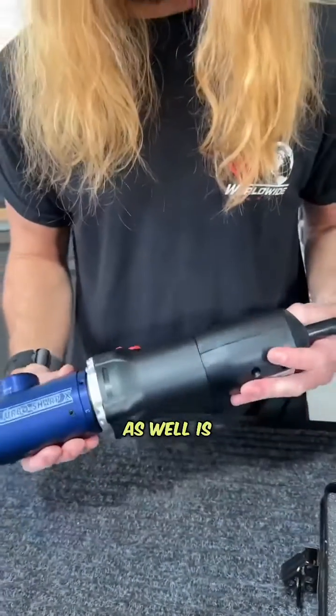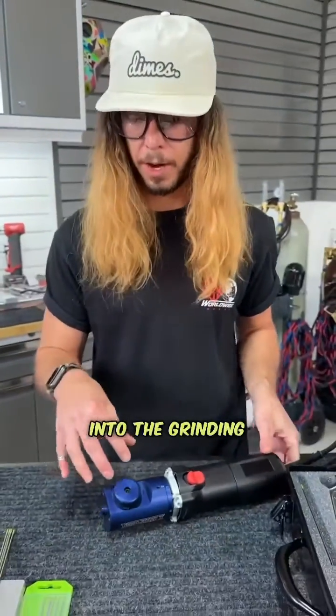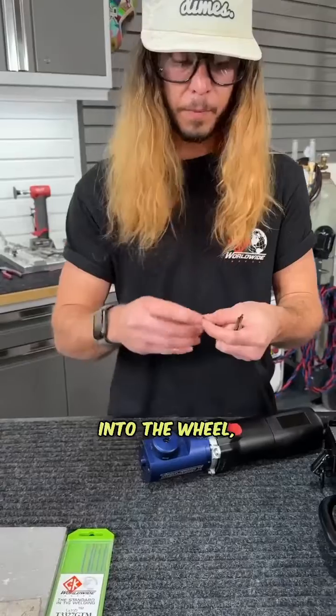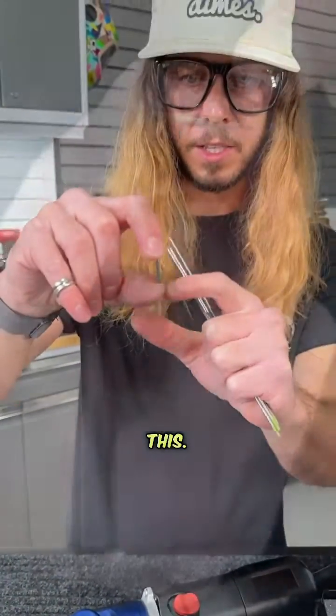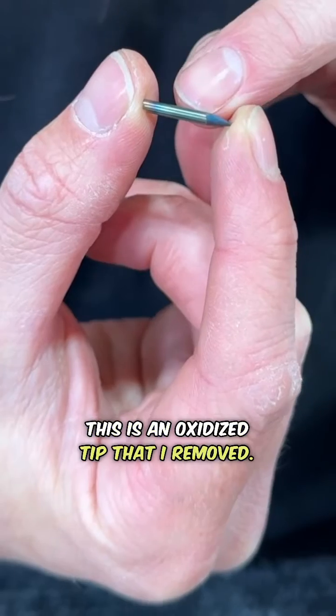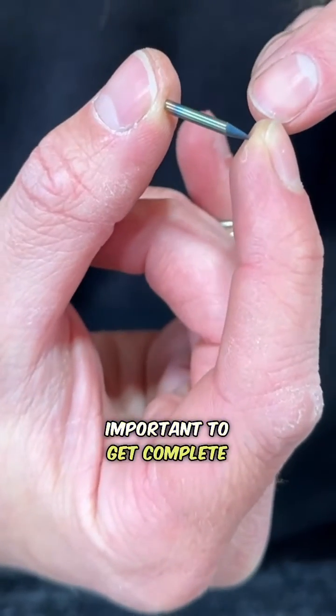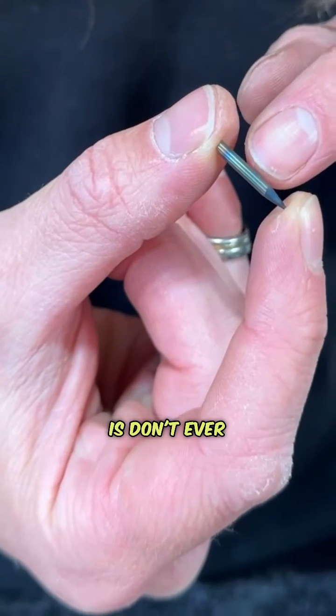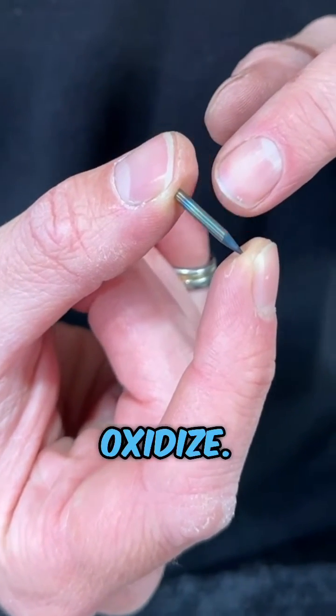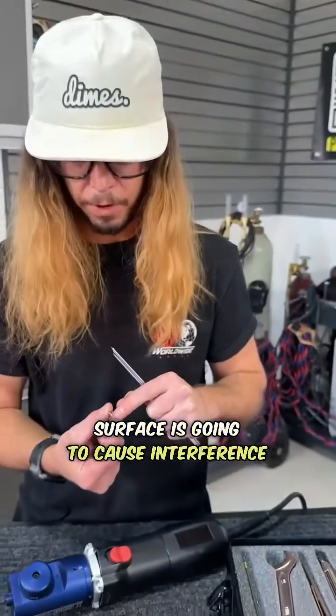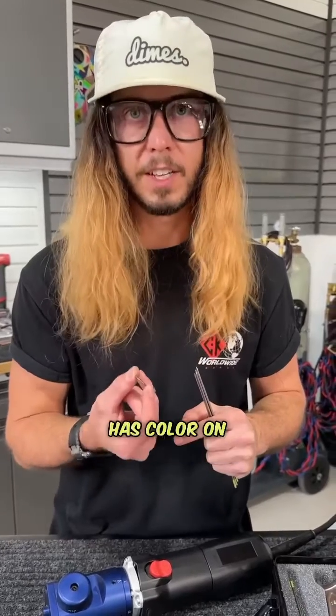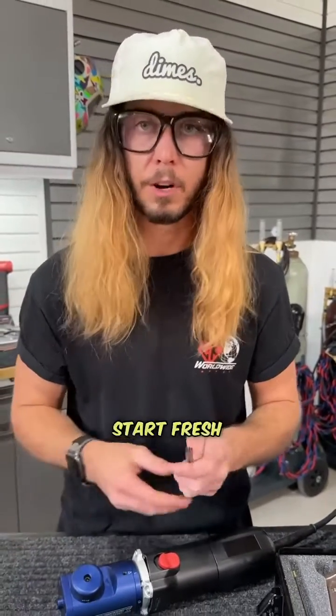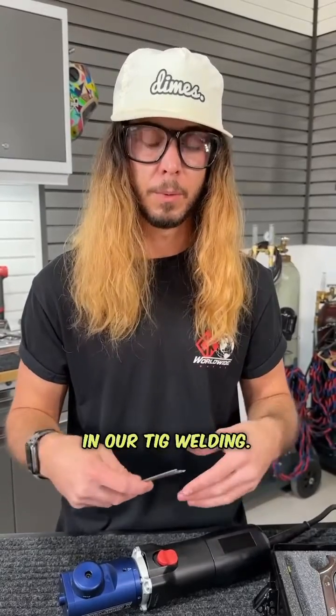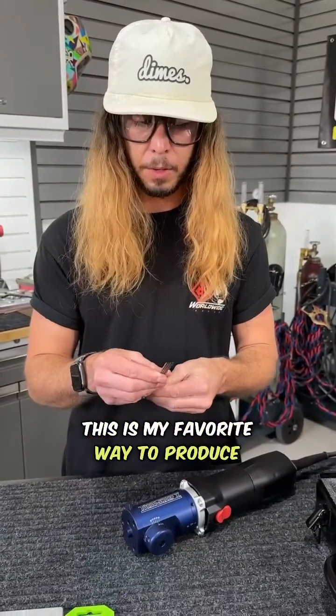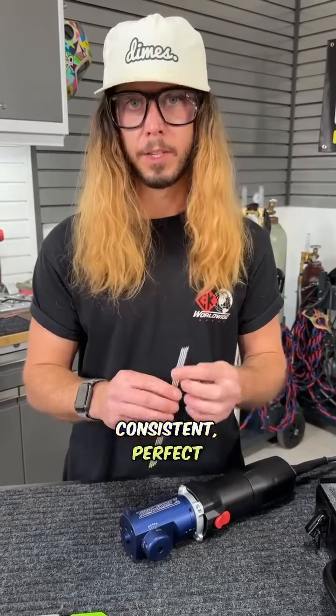Something that's really important as well is never force your electrode into the grinding wheel. If you're forcing that tungsten into the wheel, you're gonna burn the electrode tip and you're gonna oxidize it. Right here you can see that this is an oxidized tip that I removed. Something that is also very important to get complete arc control and stability is don't ever let your tungstens burn like this and oxidize. That oxidized layer on the surface is gonna cause interference with the electricity and it's gonna cause more resistance on your electrode, and that's not what we want. So if your tungsten has color on it, discard it, remove it, and start fresh because we want ultimate control in our TIG welding. This is my favorite way to produce a completely repeatable, consistent, perfect tungsten every time.